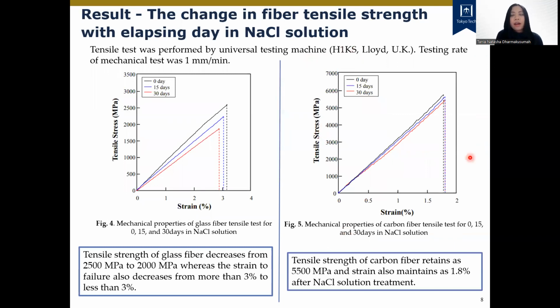And we conducted the tensile strength test. Based on this, we can know that the tensile strength of glass fiber decreases, and the strength value also decreases. But meanwhile, in the carbon fiber case, the tensile strength maintains after NaCl solution treatment.